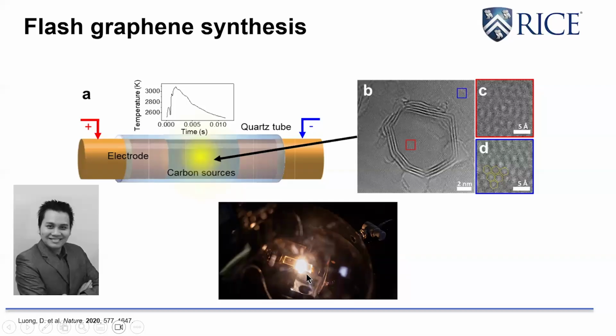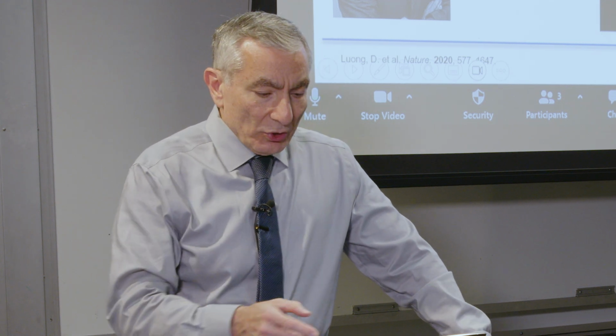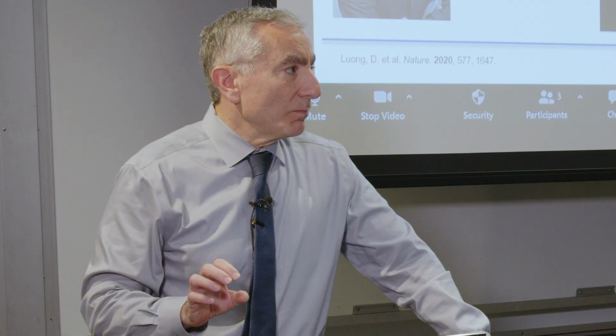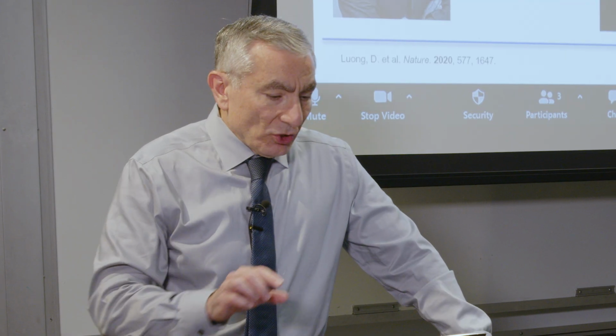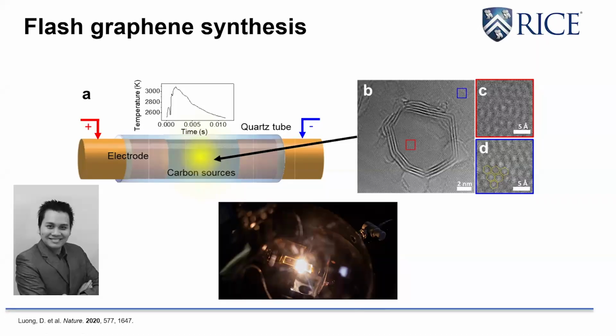That big burst of light is called black body radiation. And that's just a lot of the energy coming out as light. This heats so fast. If you have a small sample here, say like 50 milligrams, it heats and cools so fast. There's been almost no heat transfer to the quartz tube that's around it because it was so fast. And so that quartz tube is only warm to the touch after the inside has been to 3,000 degrees. So you see it's very different than heating in a furnace.